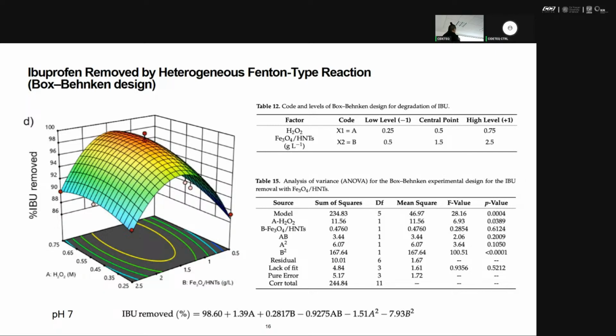And yes, I modify the quantity of hydrogen peroxide and absorbent. I use a little more to see what happened. The importance of this kind of plot is to find the curvature, to find the optimal condition and not just the tendency, because I can use more and more and more, and it is always growing, but there is a level that is not more useful. So this table gives me the optimal condition for the ibuprofen removal, which is around a dose of peroxide of 0.5 and a dose of catalyst of 1.5 grams per liter.